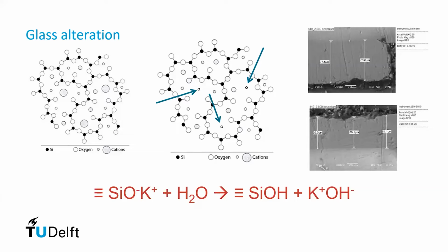So when glass undergoes an interaction with water, this is what's happening. So the glass structure changes. These cations are replaced by even smaller cations. And this is accompanied by the migration of molecular water into the glass, resulting in what you see on the right, in an altered surface layer where these cations are depleted. It has a lower density and is rich in water, so it's quite responsive to the environment in which the glass is kept.